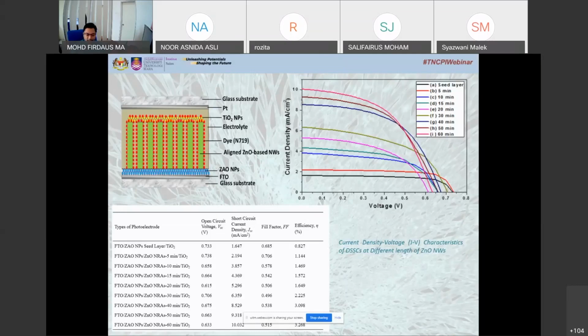So there are no wires here, just zinc oxide nanoparticle TiO2. So the efficiency we can achieve is 0.827%. Okay, but we can see when we applied the zinc oxide nanorod on top of the zinc oxide nanoparticles, as we increase the time of deposition, the length of the nanowires increased, so the efficiency was also increased. We did not test more than 60 minutes, so we do not know yet how far this efficiency can go. But I think there must be an optimum length for this kind of device fabrication.